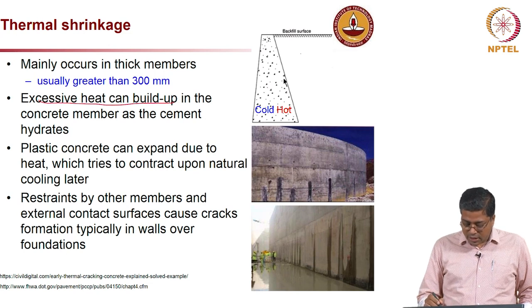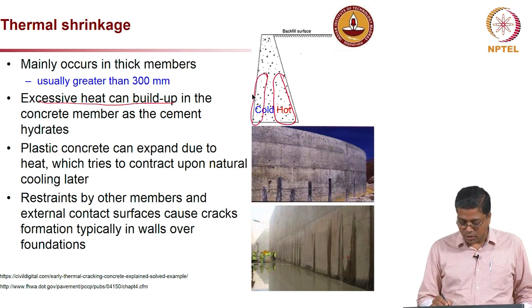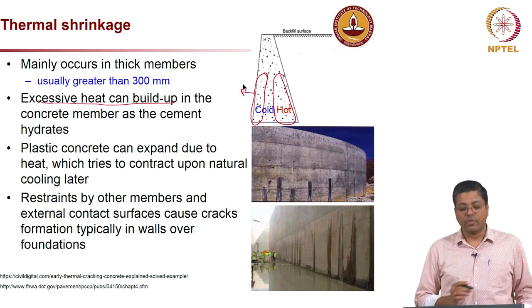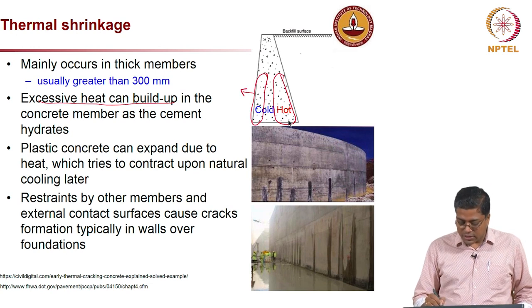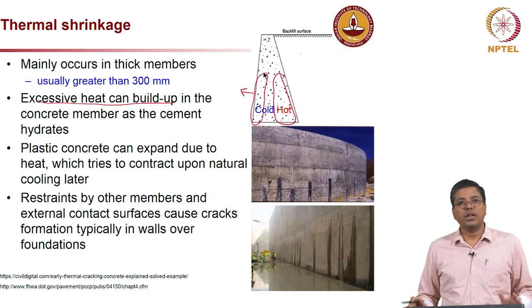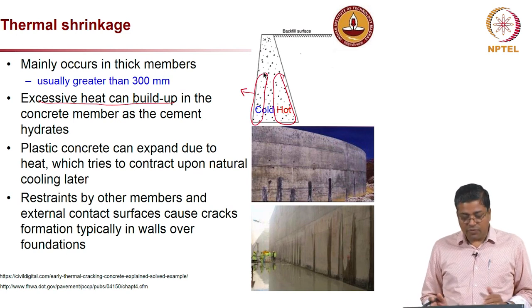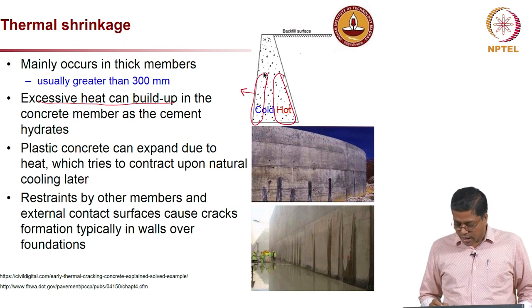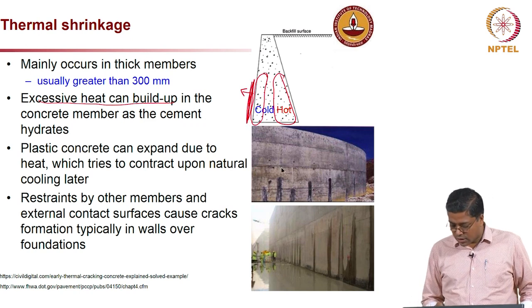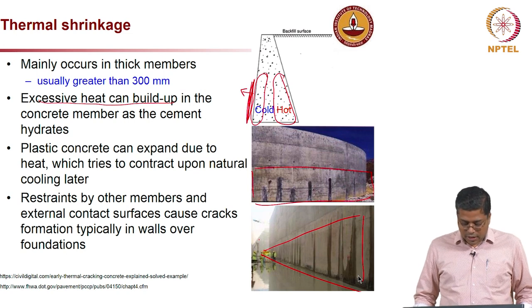What will happen is the portion marked here is a hot region, and near the surface it is relatively cold, because heat will dissipate into the environment from the outer surface, whereas the concrete inside, towards the right side in the sketch, will still remain at higher temperature. This differential temperature condition will lead to cracking, as is very clearly observed in the bottom two images. You can see two retaining wall photographs where at the bottom portion you are seeing cracking, similar to this region. This portion is cracked, and here also the bottom portion is cracking. Very clearly, this is due to differential temperature conditions.